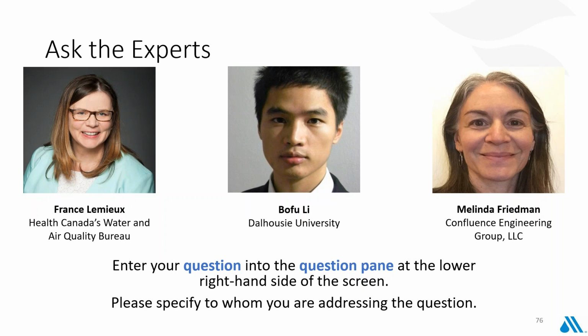Okay, our next question is for Melinda. Melinda, do you have concerns about increased iron corrosion if the buffer capacity decreases due to the higher pH? No. Well, in theory, yes. Moving up to 8.4, you're at the lower part of the buffering capacity curve. But for waters of this low DIC, the whole range of 8.2 to 8.5 is all pretty much the same for buffering capacity. We really don't see much of a change there. Plus, Tacoma did increase their alkalinity a bit, going from 20 to 25, maybe 25 to 30, to try to adjust for potential impacts there and to try to maintain that pH out to the tap.